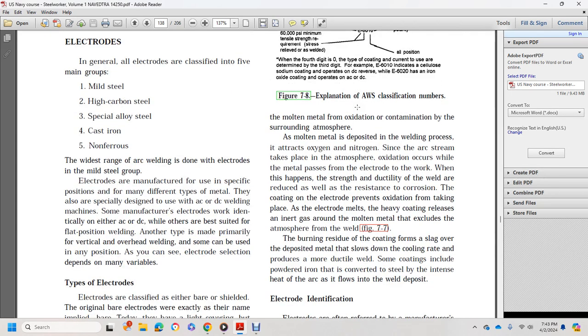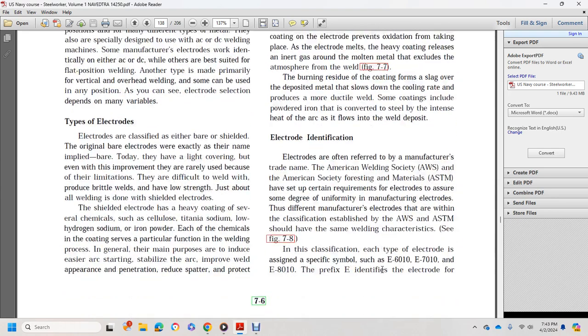Molten metal deposited in the welding process tends to attract oxygen and nitrogen, since the arc stream takes place in the atmosphere. Oxidation occurs while the metal passes through the electrode to the work. When this happens, the strength and ductility of the weld are reduced, as is the corrosion resistance. The coating of the electrode prevents oxidation from taking place. As the electrode melts, heavy coating releases an inert gas around the molten metal, excluding the atmosphere from the weld. Figure 7.7. The burning residue of the coating forms a slag over the deposited metal, slows down the cooling rate, and produces a more ductile weld. Some coatings include a powdered iron that is converted into steel by the intense heat of the arc as it flows into the weld deposit.